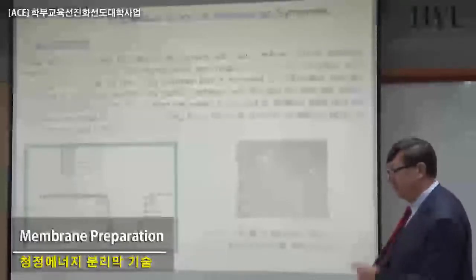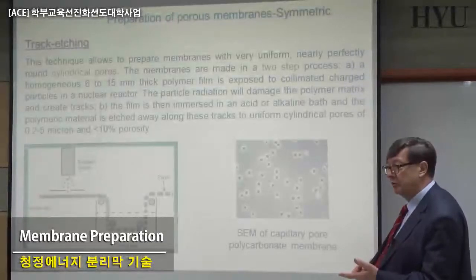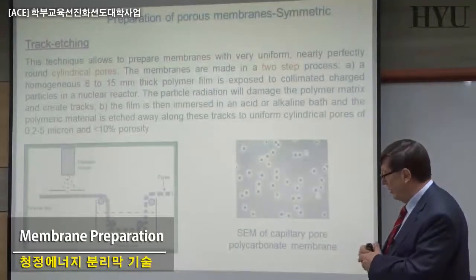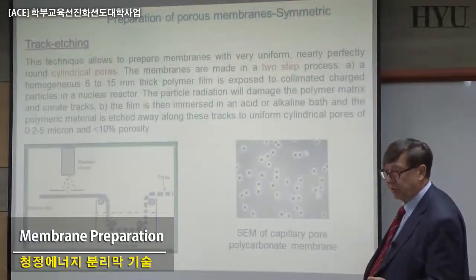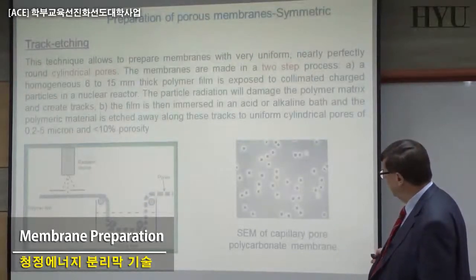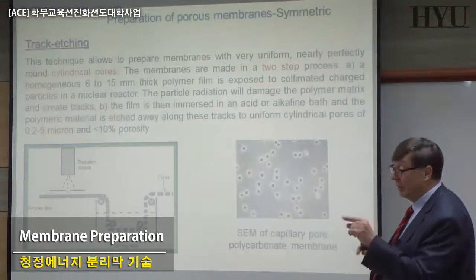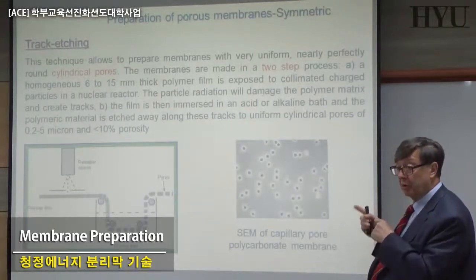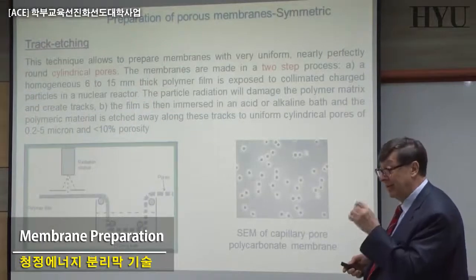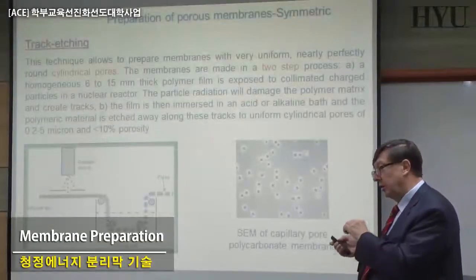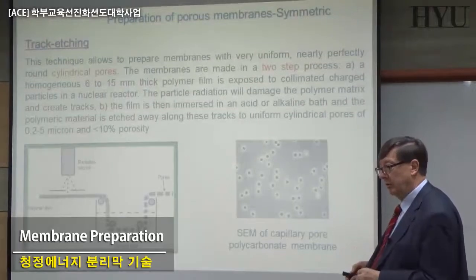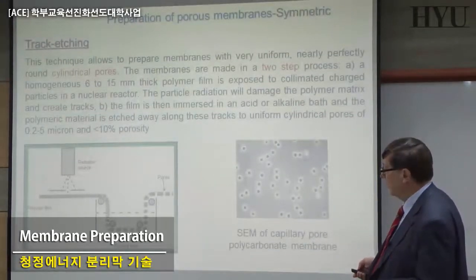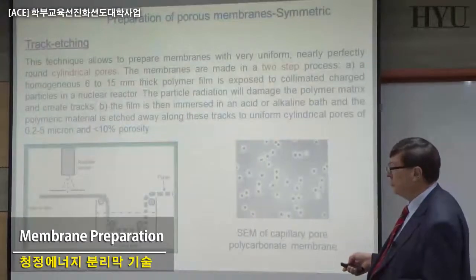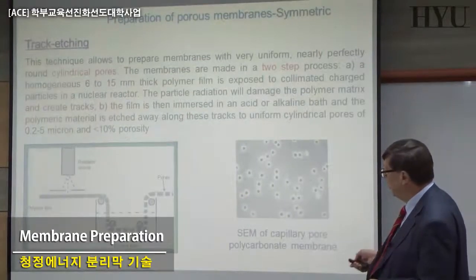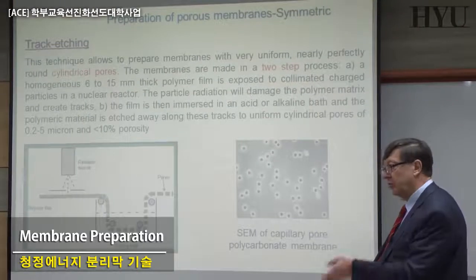This is polycarbonate, these are Nuclepore membranes. These are commercial, expensive, small scale. You cannot make a big module normally because of the cost, but you can see here the size of the pore is very regular because you can tune it depending on the power of your radiation, the intensity of the radiation, and the time that you focus on the system. You just change the size of the pore, and afterwards in the etching bath you just dissolve, and at the end you have the membrane coming out in this way.